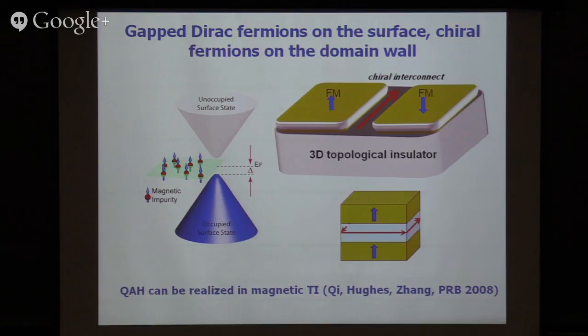And then it will open up a gap again. Actually, experimentally, people have seen that. If you put magnetic elements on the surface, such as iron and chromium, the original Dirac cone will break up, by opening up a gap. So the naive expectation is that it then becomes a really ordinary kind of insulator, because inside it's insulating. Previously, before you break time reversal symmetry, the interesting thing is the surface has a gapless Dirac cone, which is in some sense protected. But now you even open a gap on the surface, it looks like it's insulating everywhere.